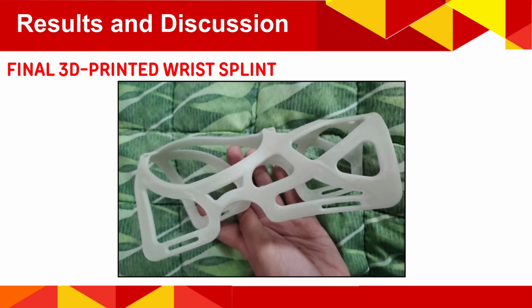This choice improved the flexibility and comfort without compromising its structural integrity. As for the printing process, we used an Ender 5 Plus 3D printer with a nozzle temperature of 190 degrees and a bed temperature of 60 degrees Celsius. These parameters ensured proper layer adhesion, minimizing warping and defects. The combination of our material formulation and optimized print settings resulted in a wrist splint that is lightweight, flexible, and durable, ideal for long-term CTS management.